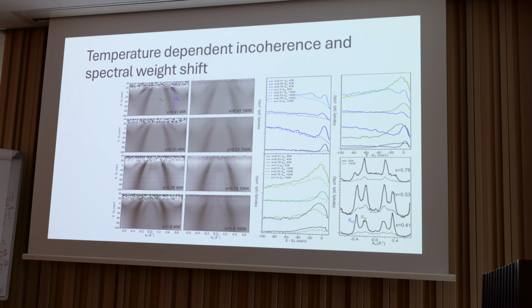On top of that, we also see this spectral weight redistribution, where not only does the XY band get less coherent, we actually see that the YZ band becomes sharper and has an increase in spectral weight. You can see that these green bands are the YZ, and they get sharper as you increase doping. That's also reflected in these MDC cuts around the Fermi level, with the outermost peak being the XY and this peak being YZ, and if you increase doping you see a shift in these ratios. So now we've seen two proxies for increased Hund's coupling influence with doping: orbital-dependent correlations and orbital-dependent coherence-incoherence, all for the DXY band specifically.